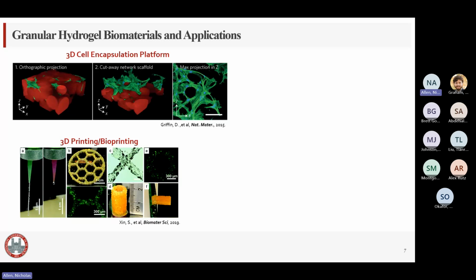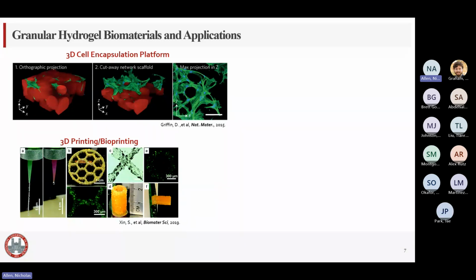And then they seeded cells onto those structures, and the microporous structure within allows for the cells to infiltrate the bulk of the material. So again, you get a much more tissue mimetic material with cells throughout the bulk of it, but with the customizability of 3D printing. On the other hand, some researchers have incorporated cells into the microporous space and then 3D printed the materials and cells simultaneously, so that, again, you have the customizability and efficiency of the 3D printing. The soft, hydrated nature of the material protects the encapsulated cells during the printing process. And then you have this nice, customized feature structure with a very consistent cell density throughout.